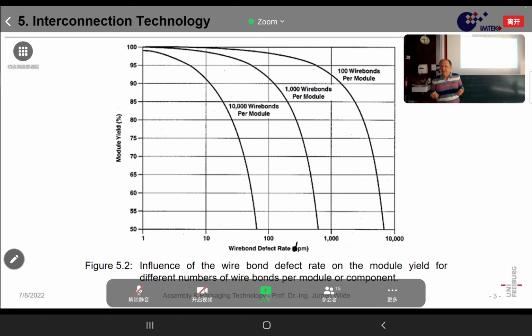you can compute what is the yield on the module level, as a function of the yield on the bond level, and of course as a function of the number of bonds you need together to operate together. So we can say, for instance, if you have 100 wire bonds, which you have on almost every IC, and you have a yield of, what is it here, 99.5% or so for bonding, then the yield of devices you get is below 50%. So, and that's the worst case. You cannot be worse in bonding.